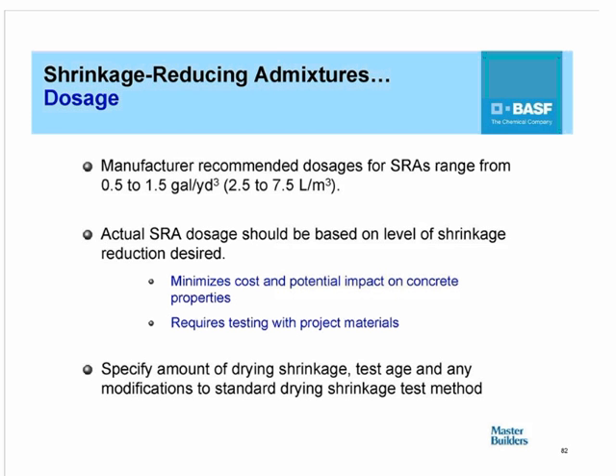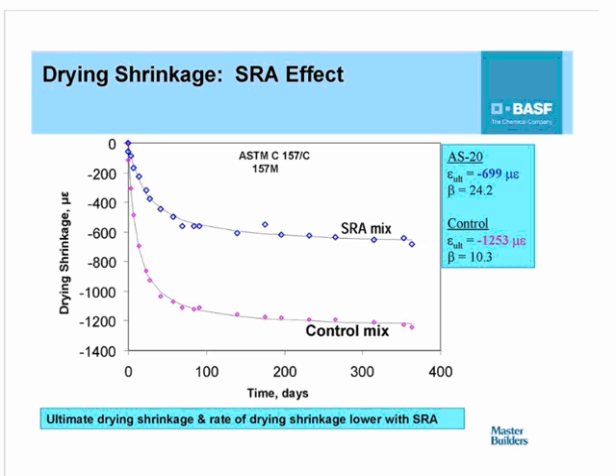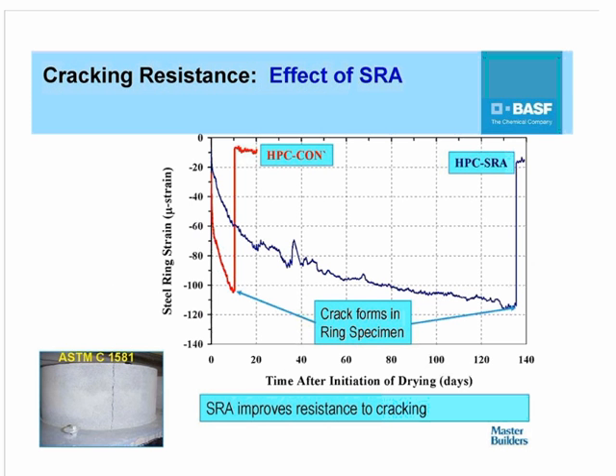A lot of times I get calls from specifiers who say that, okay, they want to use the maximum dosage, which I always advise against, because as you increase the dosage, not only do you increase the cost, but then you may also increase some of the potential impact on concrete properties, such as difficulties with entraining air and, in some instances, retardation. But these materials are very effective, and in the short term can reduce the drying shrinkage by anywhere from 50 to 80%, and in the long term, anywhere around 30 to 50%.